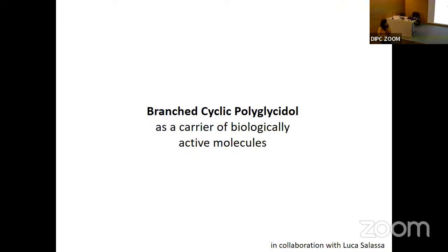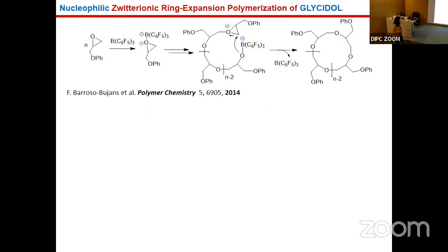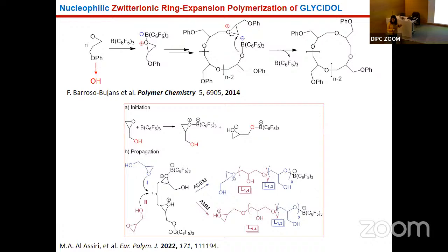This is the last part. I will explain what we are doing in our lab. This is the most recent work: on branched cyclic polyglycidol as a carrier of biologically active molecules. This is in collaboration with Luca. As I said before, in 2014, we discovered the formation of these cyclic polyethers by a zwitterionic mechanism. Okay, we said, what happens if we change these phenyl groups to hydroxyl groups, to get a hydrophilic, water-soluble polymer? We did it, and things became more complicated.